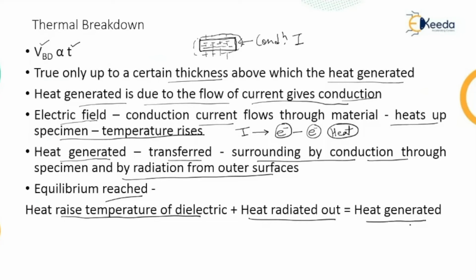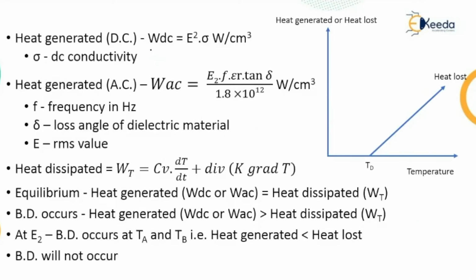The heat generated under DC stress is given by W_DC = E² σ watt per centimeter cube, where σ is the DC conductivity. The heat generated in AC is given by E² × F × ε_r × tan δ / (1.8 × 10^12), again in watt per centimeter cube. These are the two equations for the heat generation under DC and AC voltage, where F is the frequency, δ is the loss angle, and E is the RMS value of the electric field.